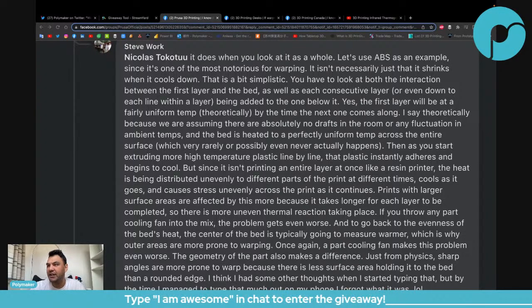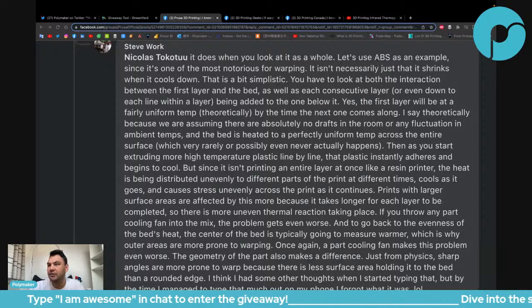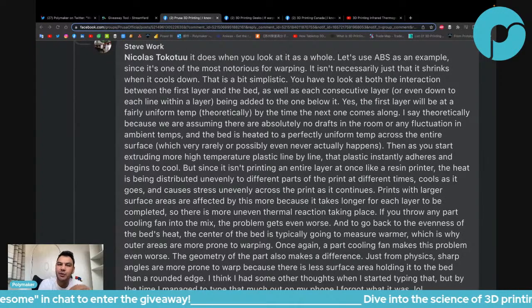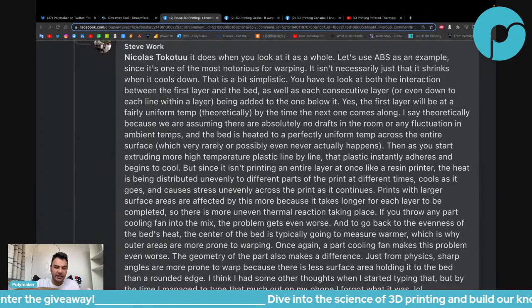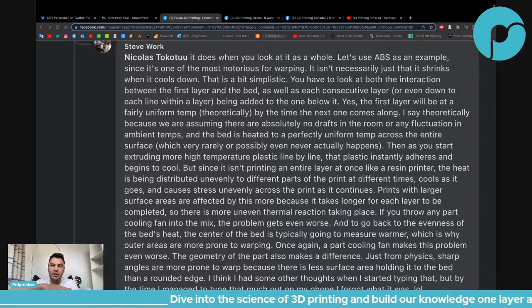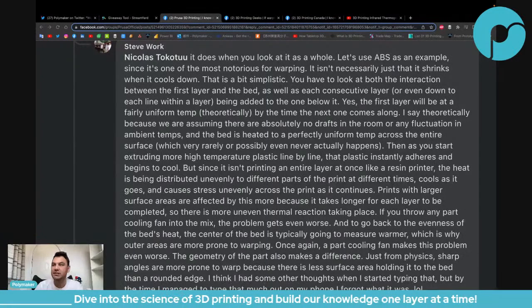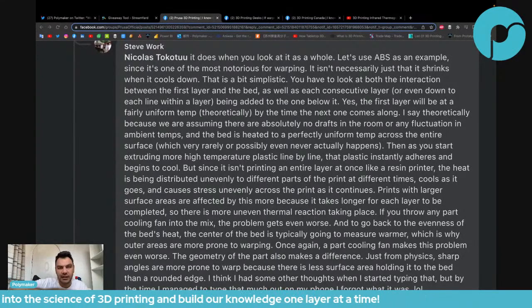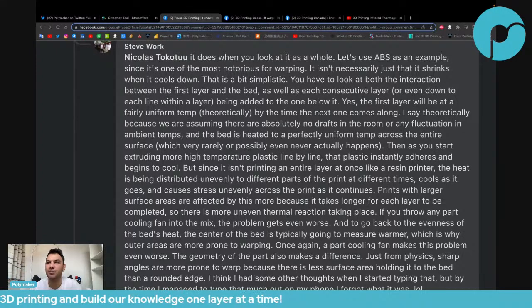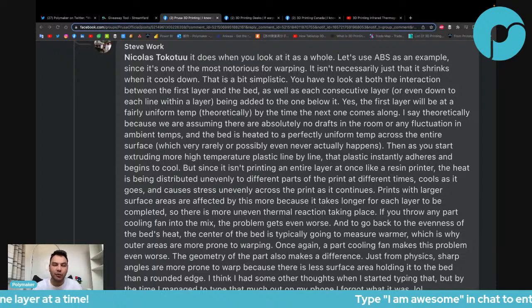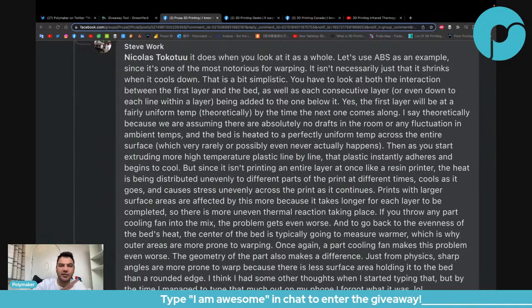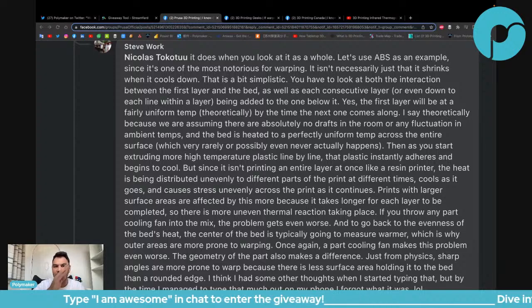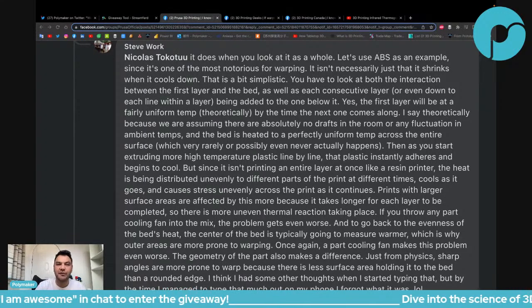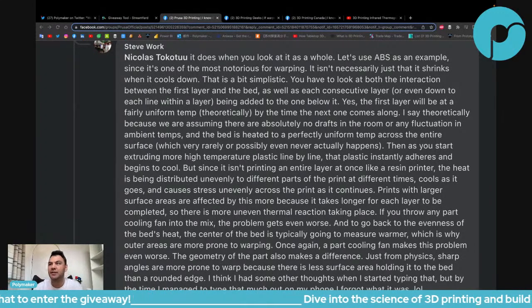Does warping happen anywhere else other than the bottom layer? Yeah, it can happen anywhere. It can happen on the bed. It can happen between layers. Anywhere, at any level, it can warp, because the stress is everywhere. It's going to warp where it's going to fail. So if the bed adhesion fails against warping, then it's going to warp at the bed. If the layer adhesion fails against warping, then it's going to delaminate.